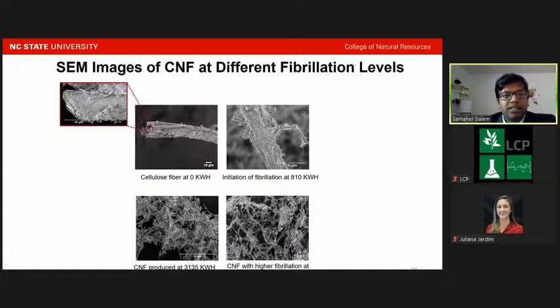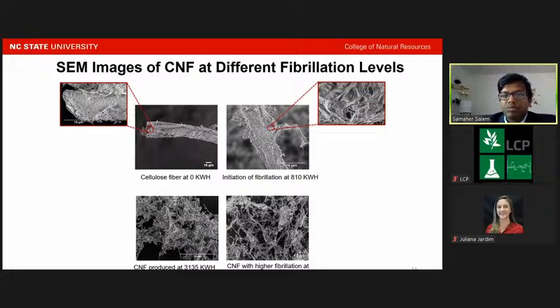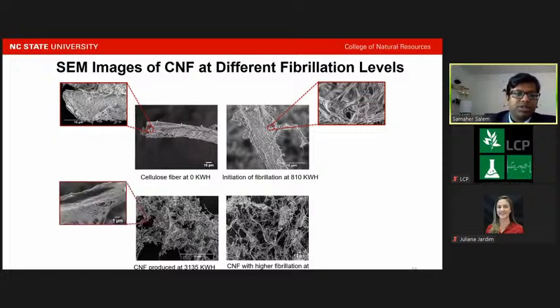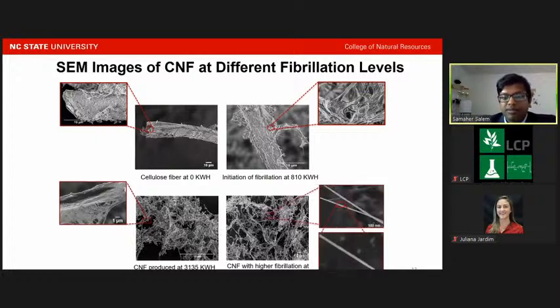And this is the cellulose fiber at 0 kWh. That means the pristine cellulose fiber. And as we add more and more energy, we could see that much, much finer fibrils were produced. And finally, at much higher energy, that's 3,135 kWh, we could say that these are the nanocellulose fibrils that we have produced.